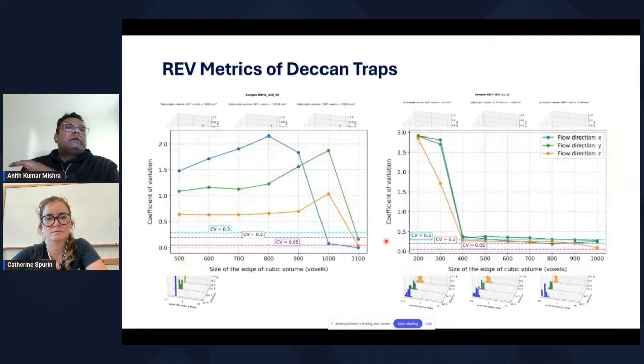And we calculated the coefficient of variation as well. For siliciclastics, we are very familiar that we typically use a 5% or 10% coefficient of variation, but we never get that for the basalt networks. So we relaxed our coefficient of variation to 20% and sometimes to 30%. This is a relaxed threshold value that we had to use for our basalts, because it never converged to 10% or 5% values because of the heterogeneity.